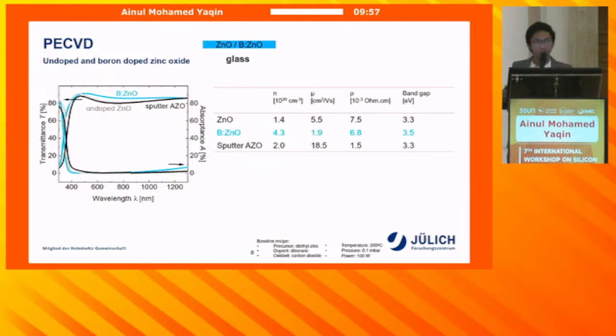Initially, we did some process optimizations to get good optical and electrical properties of our zinc oxide films. If we look at the optical properties right here, we can clearly see that the film that we developed is promising. It has good transparency and low absorptance, which is quite comparable to the reference sputtered AZO. And if we compare the undoped and boron-doped zinc oxide, you can also see the absorption shift in the boron-doped zinc oxide due to the larger band gap, which is understandable.